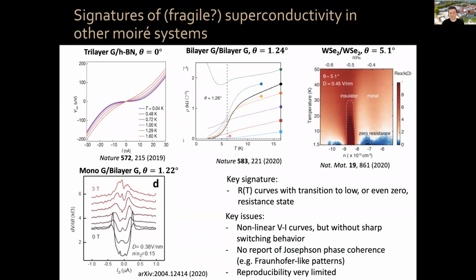However, there are some key issues. For example, there are nonlinear VI curves, but they're smooth, without sharp switching behavior. In any of the systems, there's no sharp switching behavior. And perhaps more importantly, there's no report in any of the systems of Josephson phase coherence from Fraunhofer-like patterns. And the reproducibility is also very limited for this type of data and the different structures. So superconductivity may well still be there, but if it's there, it seems that it's very fragile and not very robust.